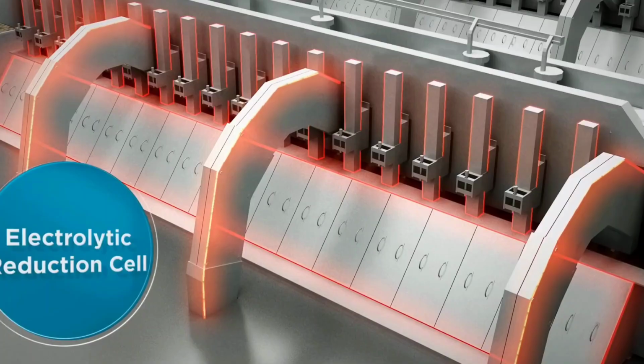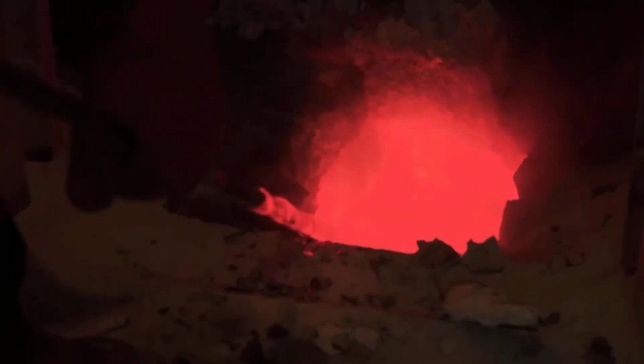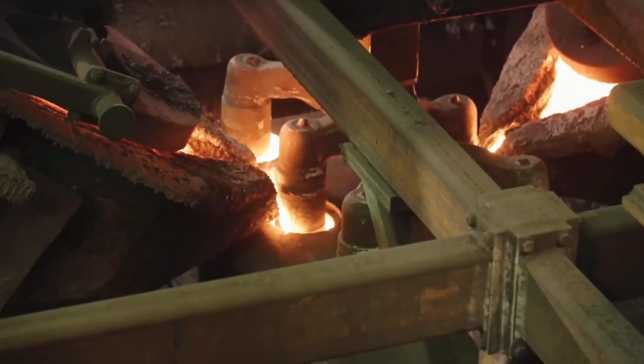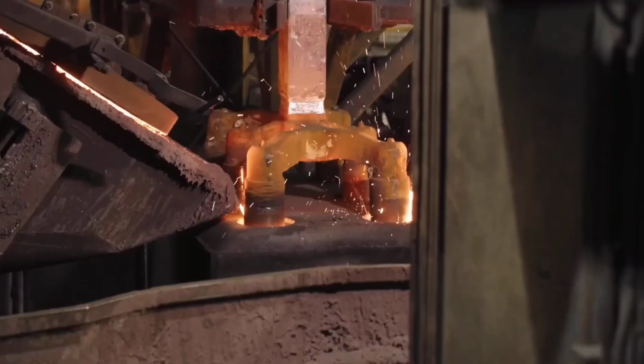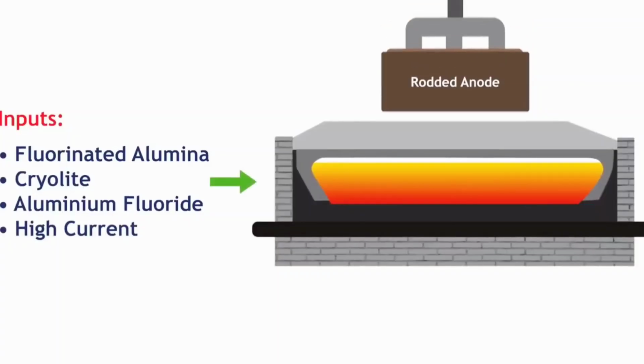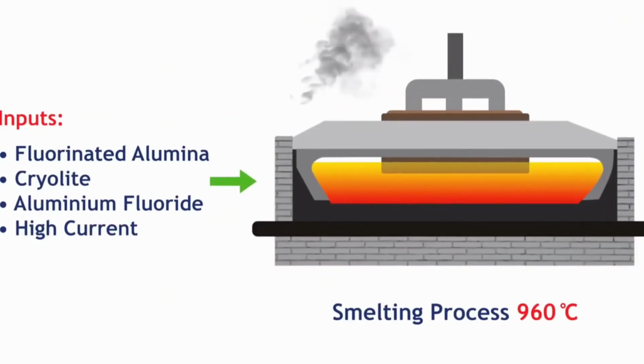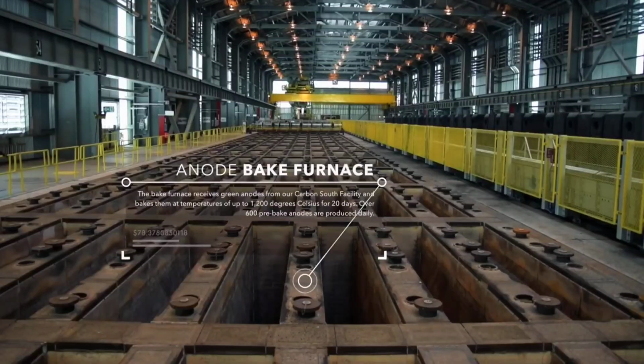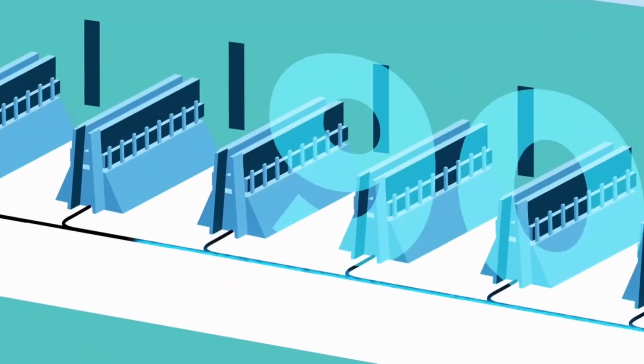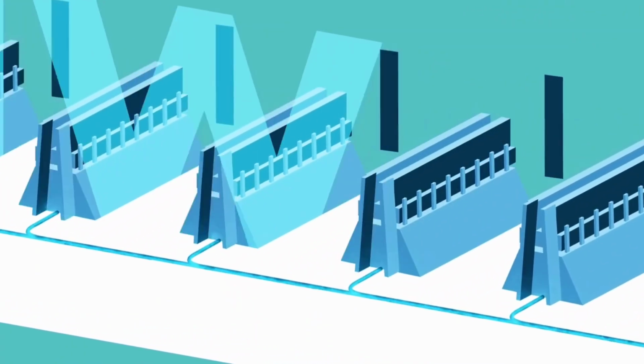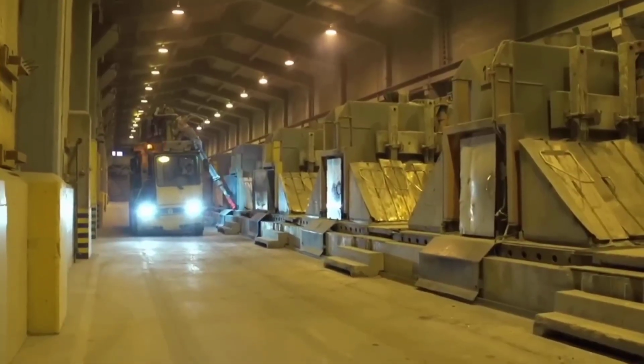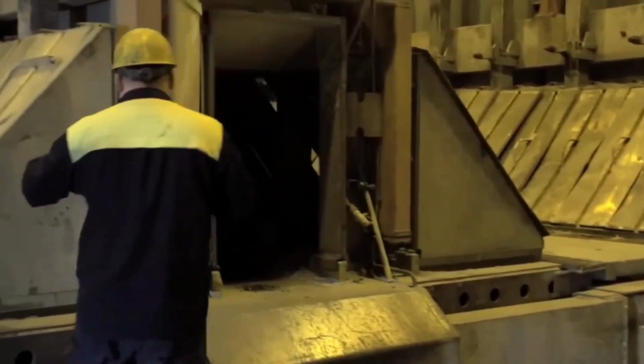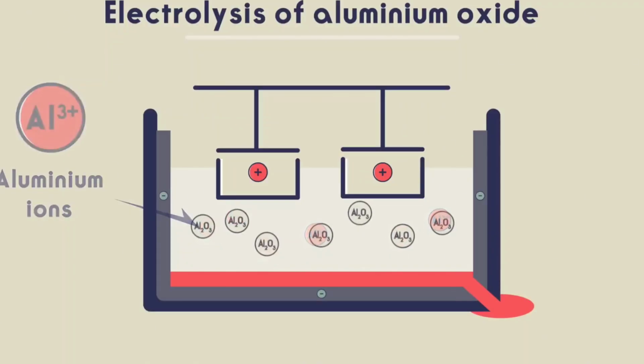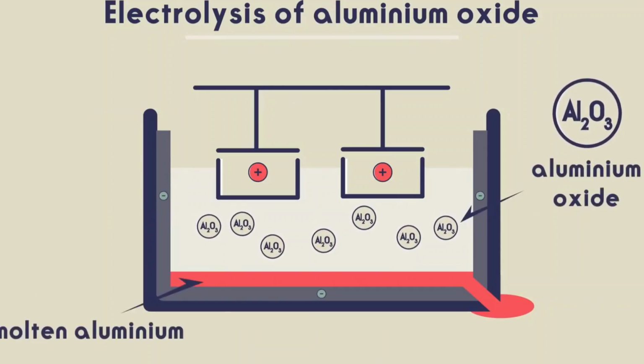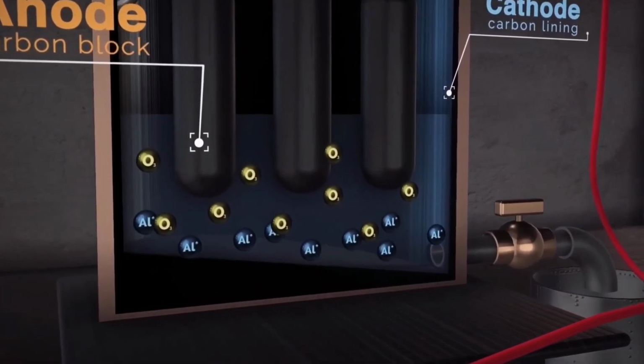After refining, the aluminum oxide is dissolved in molten cryolite and fed into massive electrolytic cells operating at temperatures between 1742 degrees Fahrenheit and 1832 degrees Fahrenheit. An immense direct current, on a plant-wide scale, 900 megawatts for the entire line, flows through the cells, breaking the bond between aluminum and oxygen. Molten aluminum settles at the bottom, while the oxygen reacts with carbon anodes to form CO2.